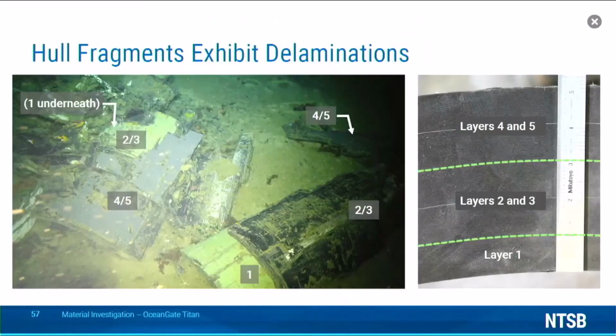Okay. Also of note for this piece, the outer shell consisting of layers 4 and 5 was fractured through the layers, and a chunk of it was missing, which is why the top surface of layer 3 is visible. These through thickness fractures were not found in the middle shell.